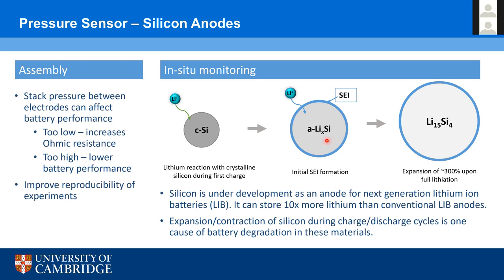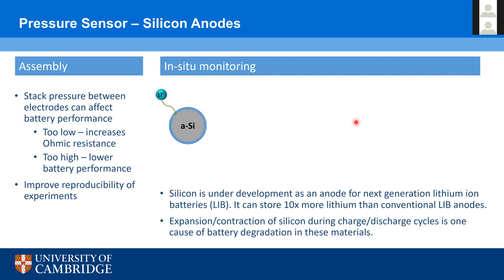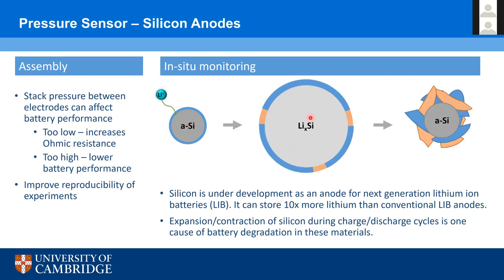The other interesting thing is that at low voltages you get this electrolyte breakdown layer, the solid electrolyte interphase, where the electrolyte breaks down and forms a passivating layer on the surface of the silicon. Then in subsequent cycles, the silicon contracts when you delithiate, and expands again as you relithiate it.